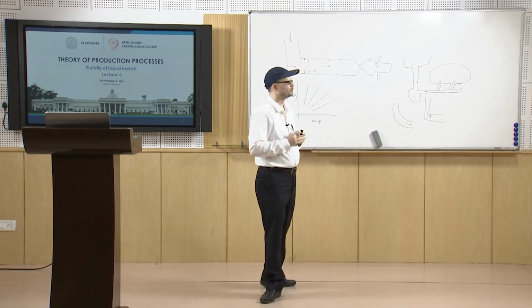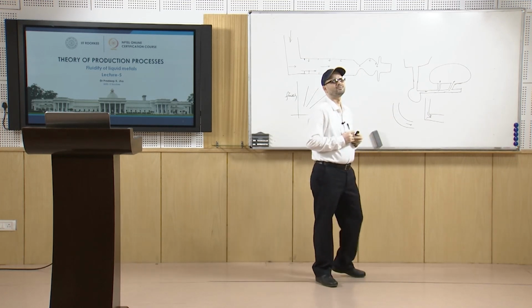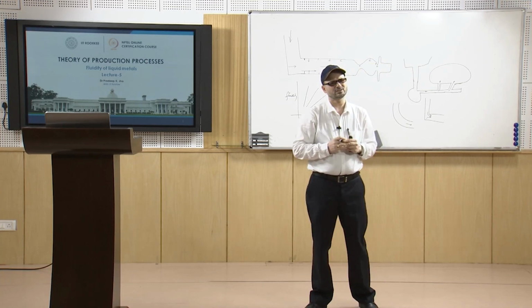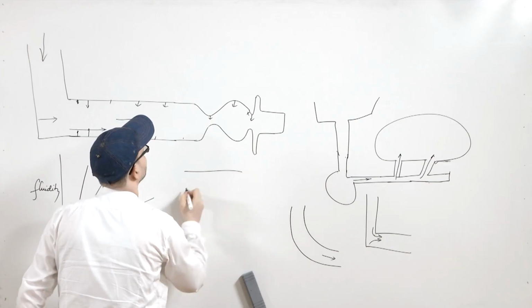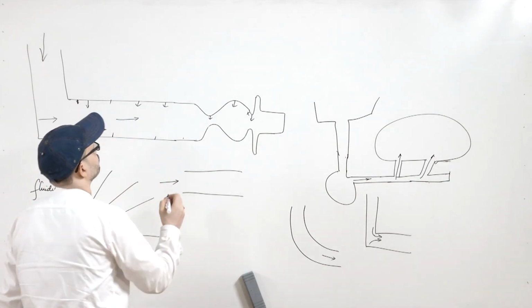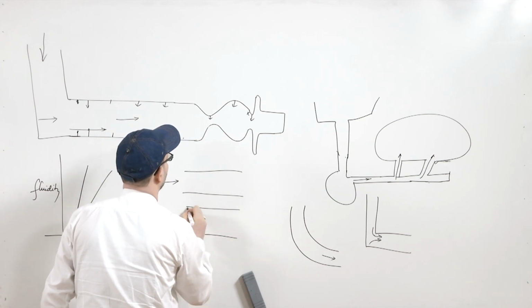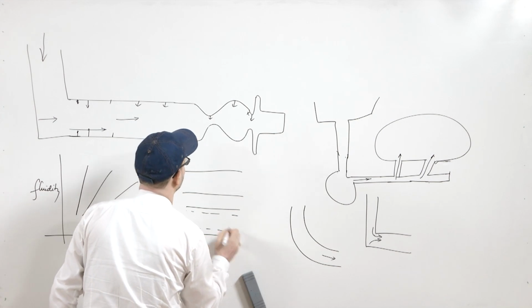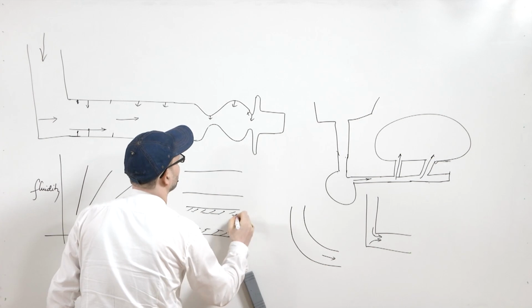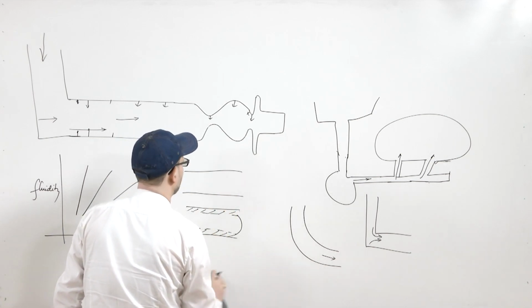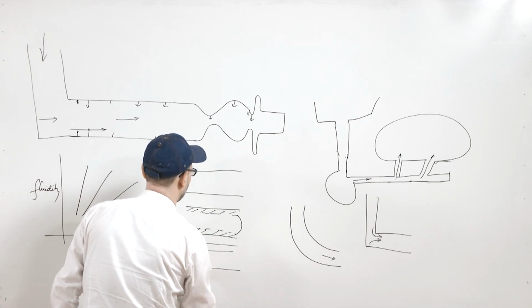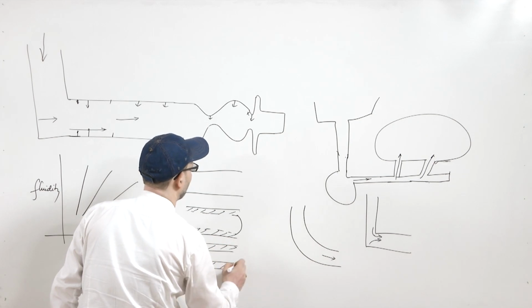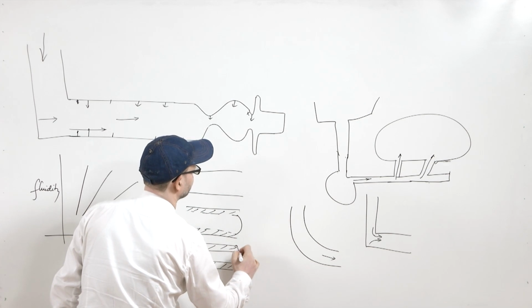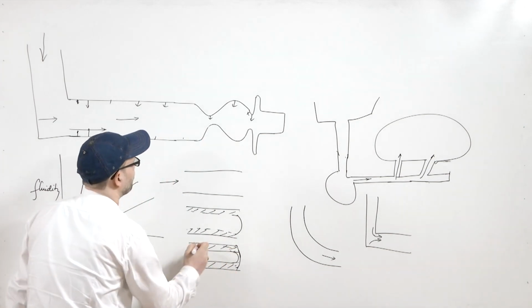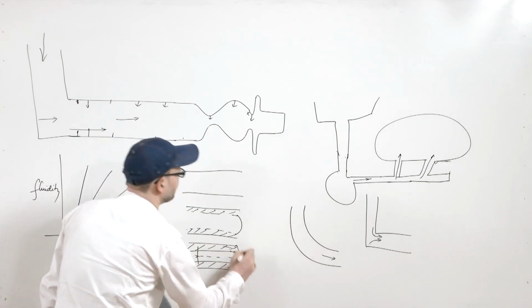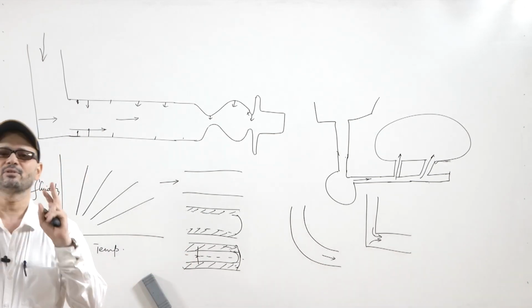In case of pure metals, as you know, the freezing is by advancing front, because you have plane front solidification. What will happen if you have the channel and the liquid metal comes? Slowly, after some time, you will have surfaces here and here solidified, and this will be your surface like that. After some time further you will have this and this. This portion is solidified, this portion is solidified, and then your advancing front moves like that. You have this much portion solidified, and when both are matching at this point, this basically is choked. That way it will stop.